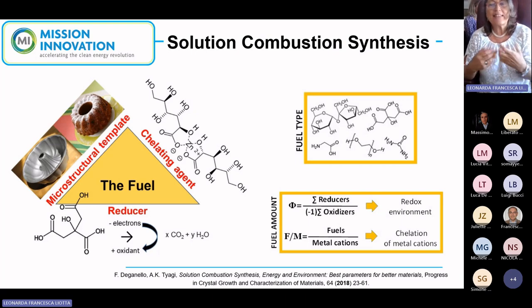The other influences the chelation of metal cations and the formation of the network, and also the porosity, because when we use a lot of fuel, we have too many spaces in the network during the combustion, and this could have positive or negative effects depending on the materials. But for sure, it will affect the morphology, the homogeneity of the powder and the final properties. If you want to know more, you can read this review from some years ago.